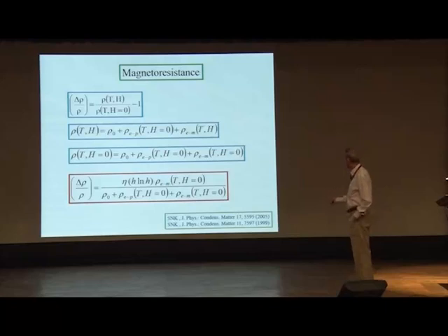So in this expression, the only variable is this, eta. Eta only provides for the surface spin disorder, and how that changes when you apply an external field, and how the electron-magnon scattering at the surface would take place. So there will be some extra contribution coming from the surface, which is not accounted for in theory. Theory was done for a homogeneous system where there was no disorder. So it is just to take into account the disorder.